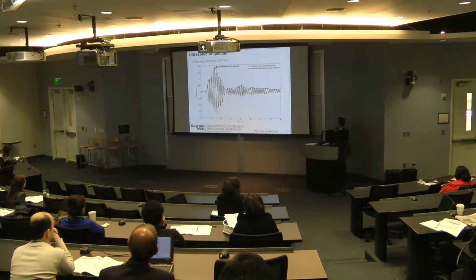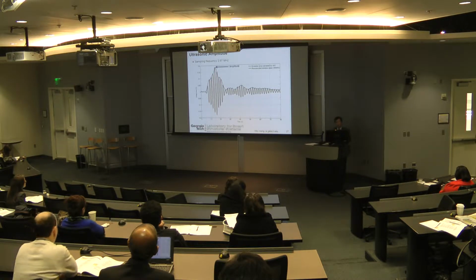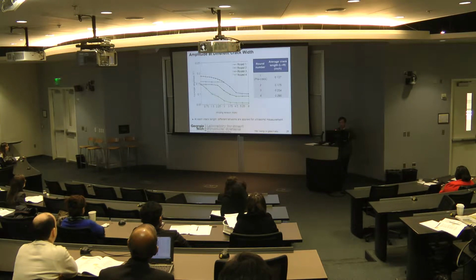And we get the received signal, we calculate the amplitude. We're using a very simple processing technique here. Just gather the amplitude. So if a crack happens or grows, that amplitude value is going to reduce. And that's exactly what we have observed through the test.